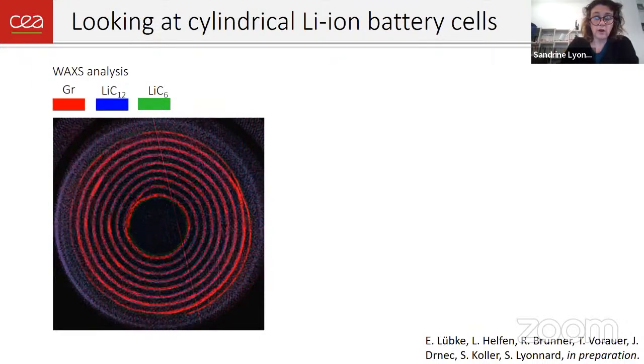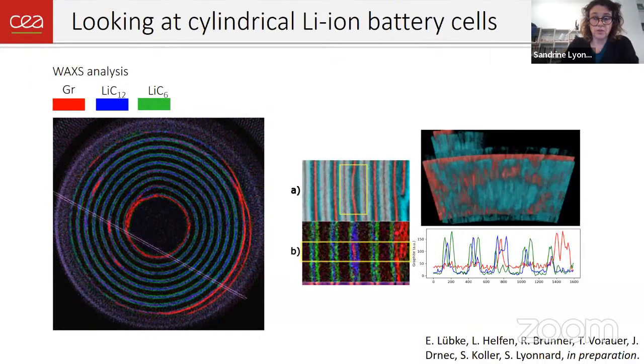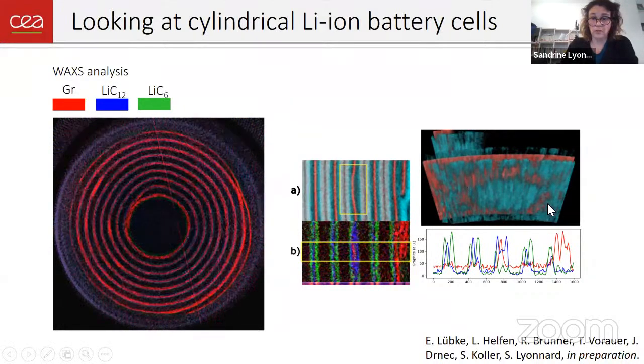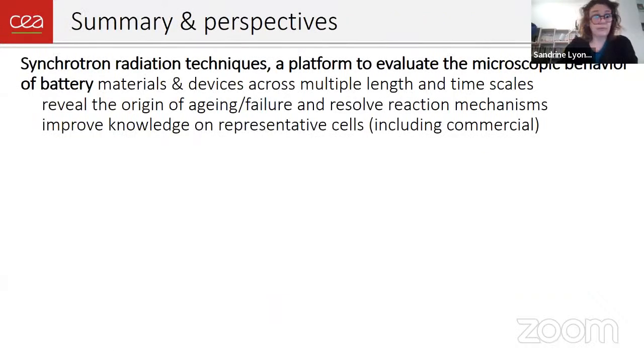And we correlate these defects with the neutron data, because those are exactly the same cells we're looking at. And we see that the depletion of lithium we've seen with the neutrons is completely correlated to some localized defect zone that is disconnected and is not working anymore in the battery. So the correlative analysis of neutron and X-ray data is very important, because it is the only way you have, in this case, to really understand the origin of this defect, which is causing some degradation of the cells in the long term. So I'm reaching the end of my talk.